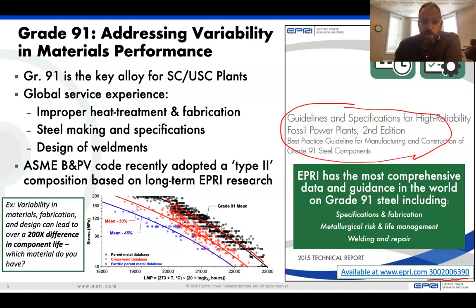By virtue of having a weld in the material alone, you get a degradation in strength. And while it may not be apparent what that degradation in strength is, you can actually lose a factor of 10 on life. So if you put a weld in a specific stress orientation, you may see up to 10x reduction in life of that component.